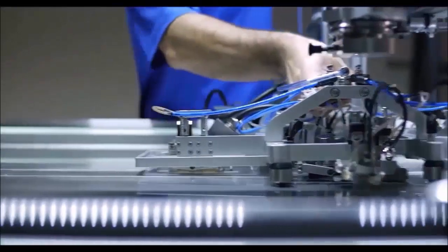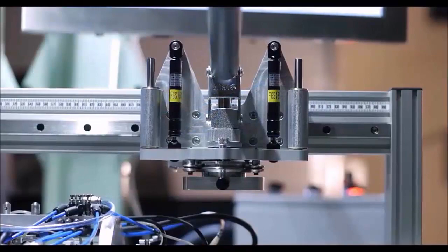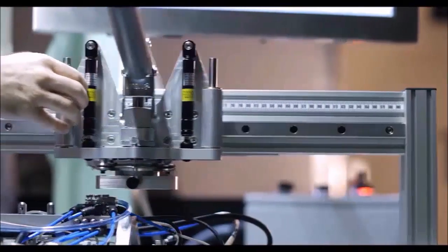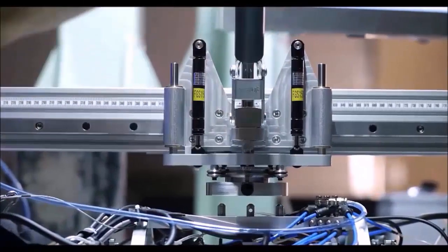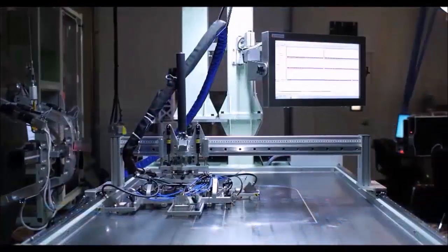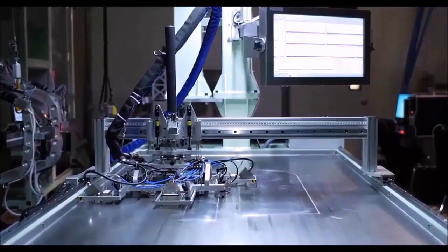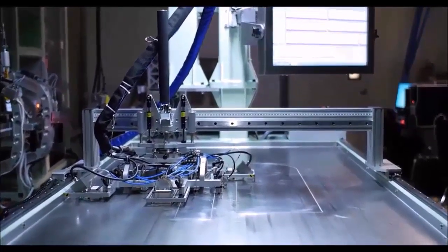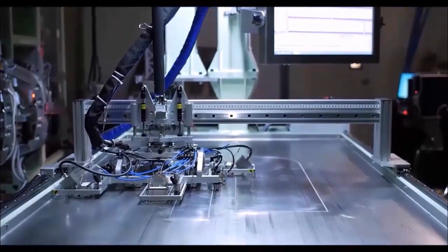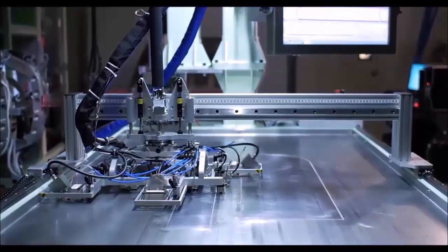In order to allow for an efficient and rapid calibration process, the complete probe pan can be easily removed from the inspection robot and installed on the calibration table. A quick connection system allows it to attach the probe pan to an XY scanner integrated with the table. The calibration blocks with appropriate reference reflectors are embedded in the work surface of the table. They are used for initial calibration and characterization as well as periodic checking of the system.